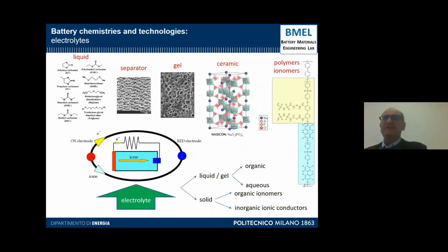Regarding electrolytes, a wide range of materials can be employed, the most common of which are porous membranes soaked in solvents with dissolved ion salts, gels, in which essentially the same solution is incorporated within a polymeric framework, ionically conducting ceramics for the famous solid-state batteries, and ionomers.